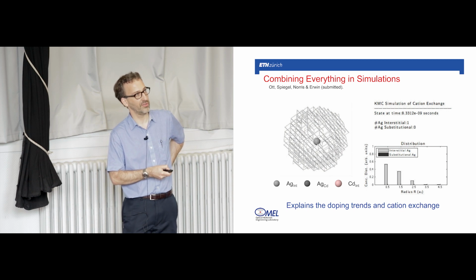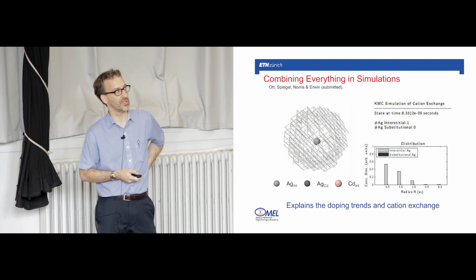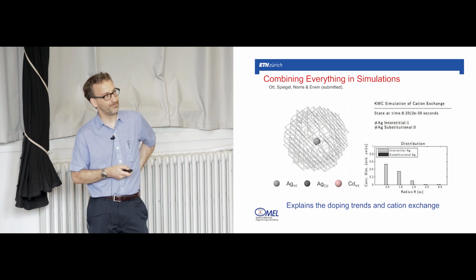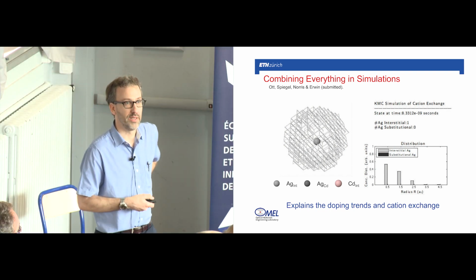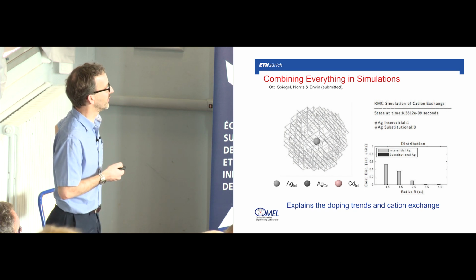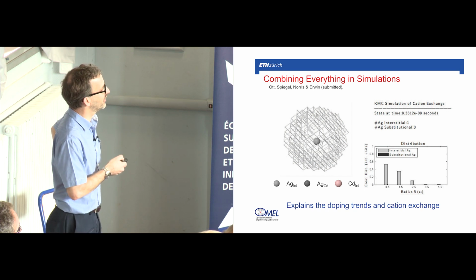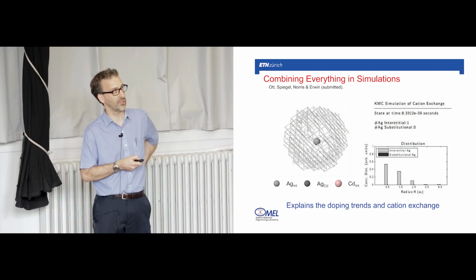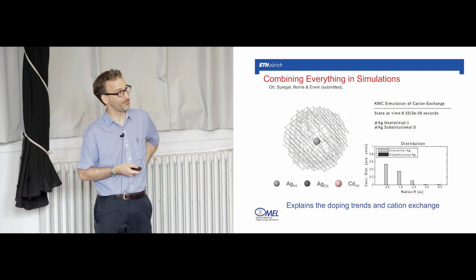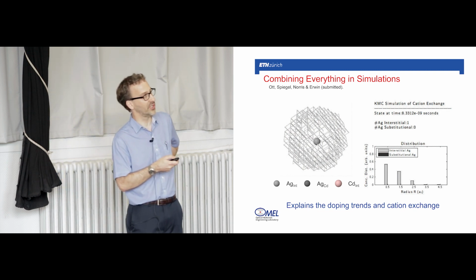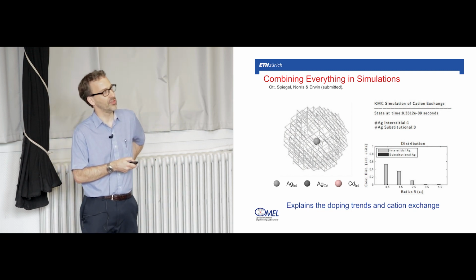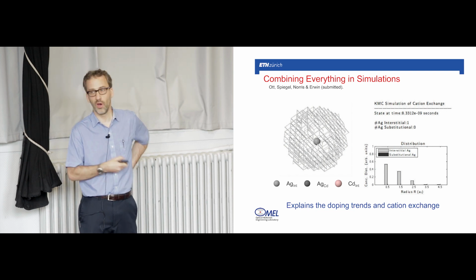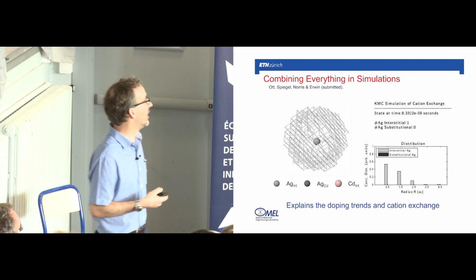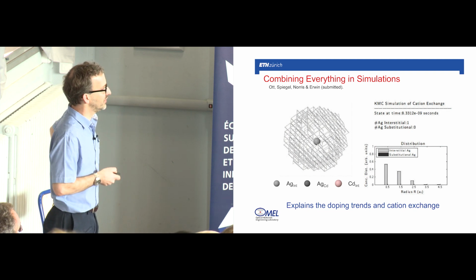So the average position of these cations will shift towards the surface as we add a third one and then a fourth one in this simulation. We're just slowly adding silver into the particle, and eventually they get pushed out towards the surface, and one of them gets close enough that it does one of these kick-out reactions, and it immediately attracts interstitial silvers and starts to nucleate a little Ag2Se phase. If you speed this reaction up now, you can see that as you add silver, this new Ag2Se phase basically starts to grow on the surface, just like the experiments seem to suggest.